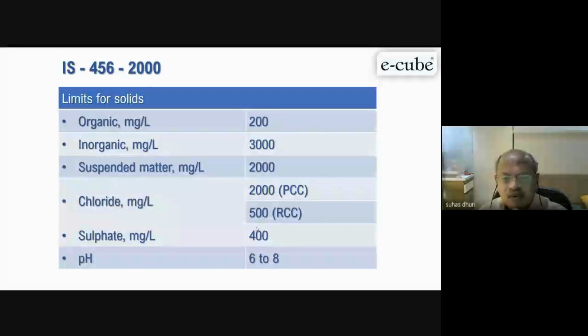For sulfate, 400, because you may get sulfate attack. As I said, sulfates and aluminates in the cement will react and form calcium sulfoaluminate, which is always in the form of a gel and it swells. Once it swells, it disturbs the concrete structure and it starts cracking. That's why instead of normal OPC you go with SRC, sulfate resisting cement, or we can have other combinations that we'll discuss during properties of concrete.